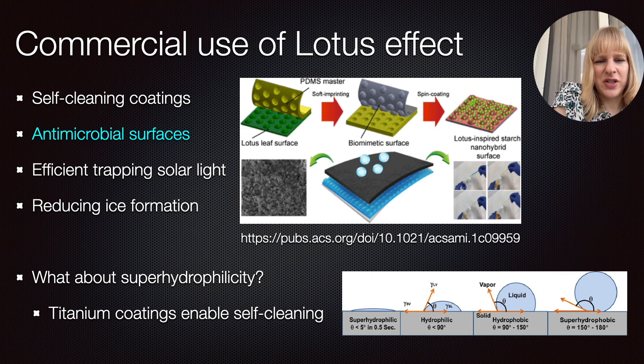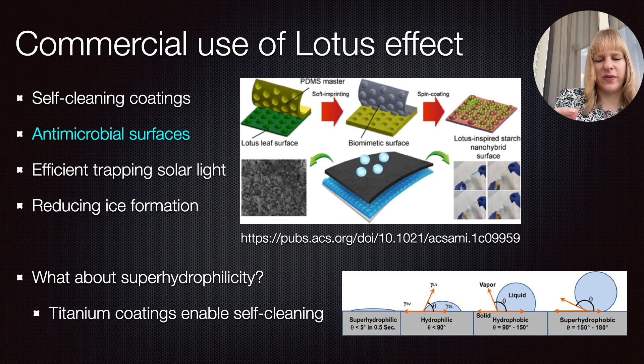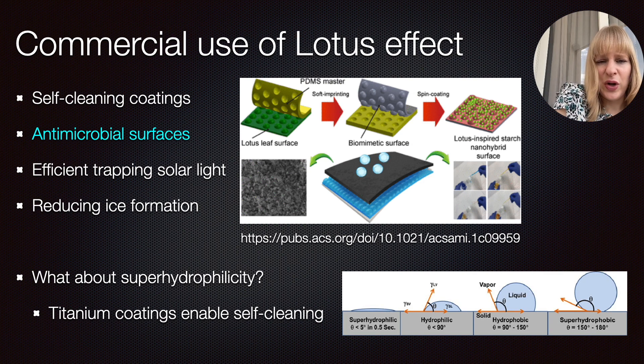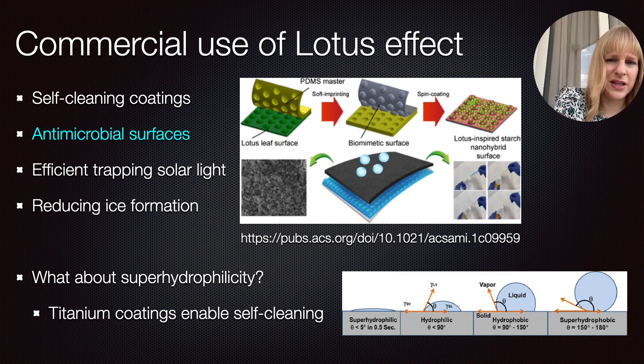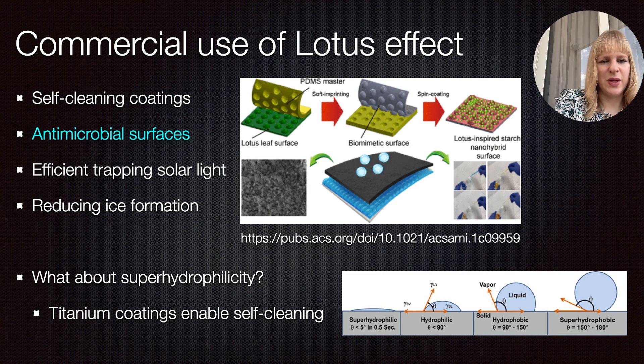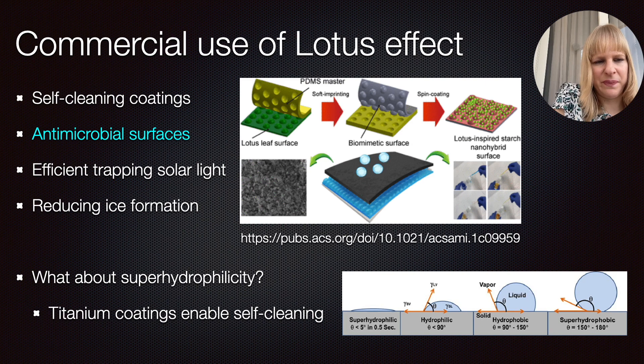Typically, anything hydrophilic has a contact angle below 90 degrees and anything hydrophobic has a contact angle between 90 and 150 — hydrophilic spreads out on the surface while hydrophobic assumes a spherical shape. For superhydrophobic surfaces the contact angle is typically between 150 and 180, with about 170 degrees typical for the lotus leaf. On the other hand, for superhydrophilic surfaces, a droplet of water would completely spread out over a surface within seconds. We found that both ends of the spectrum have a similar self-cleaning effect, and this can be achieved with titanium coatings.